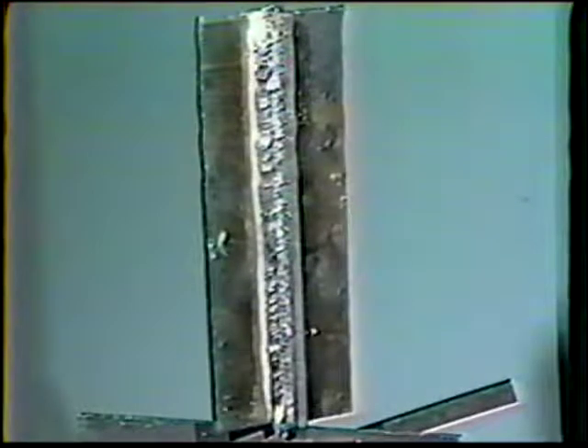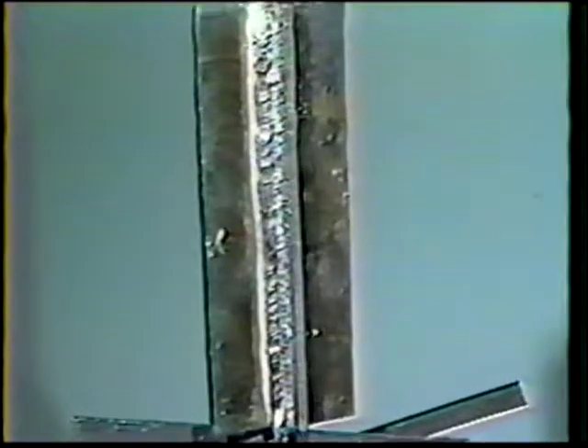The finished weld should be 1/2 inch wide, flat to slightly convex, and show no undercut along the toes. Inspect the weld and deposit the final beads on all the remaining workpieces. Now, if desired, a visual and macro etch test can be performed on this weld using the procedure outlined in Topic 11 for the V-groove weld.